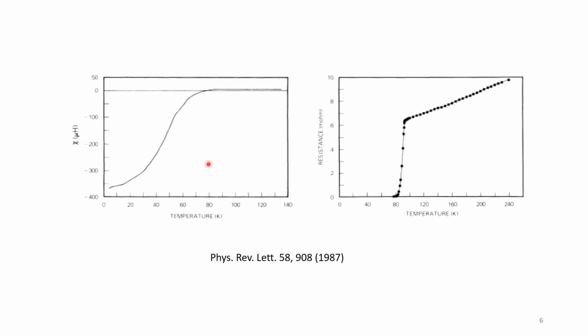So this is exactly what is being shown. So this is another paper. This is some different superconductor. Here you can see that at the same temperature at which the resistance drops to 0, right around 81 or around 85 Kelvin, you see a similar transition in the susceptibility. It starts becoming negative. This concomitant presence of these two features is what defines a superconductor. Just alone this wouldn't really be a convincing proof.